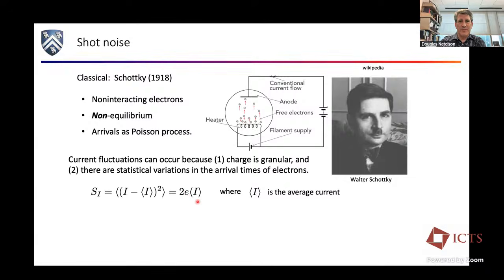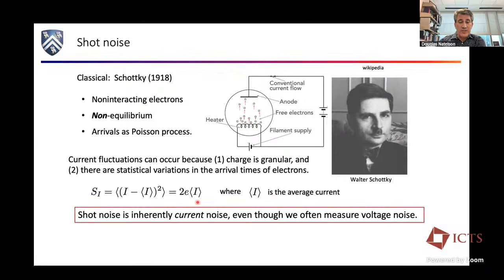It's also a pretty good treatment for an ordinary tunnel junction. Shot noise is inherently current noise. It's a little bit of a technical point: in the experiments, we actually are measuring voltage noise and converting back into current noise using the differential resistance. A parameter that shows up all the time is the Fano factor, which is basically the ratio of the noise that you measure to the Poissonian result.